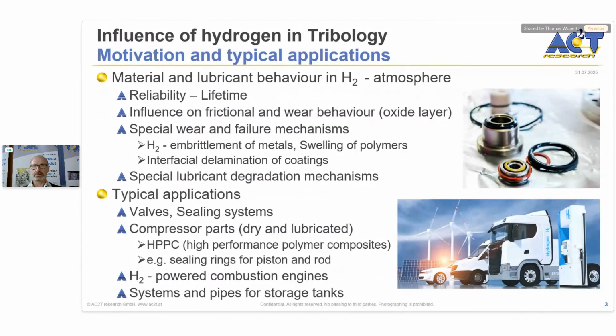So as already mentioned by the speakers before, it has an effect on the material and lubricant behavior. So this causes a reliability and lifetime issue. It can have an influence on the frictional and wear behavior, for example, by preventing or removing an oxide layer in metals, which is usually formed with present oxygen. So this might be prevented in a pure hydrogen atmosphere. It can cause special wear and failure mechanisms like hydrogen embrittlement in metals, swelling of polymers under high pressure. It could cause interfacial delamination of coatings. It can have effects on the lubricant, can cause special degradation mechanisms.